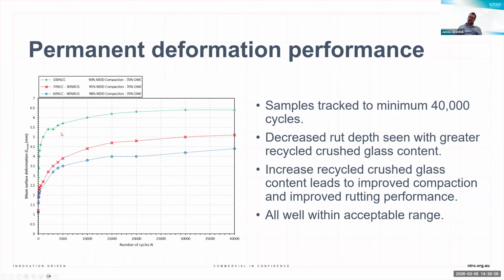Actually, the 100% recycled crushed concrete wasn't that bad in terms of permanent deformation performance under the heavy wheel loading. The test that we undertake, we test under up to 40,000 cycles. Typically, the correlations have shown that if we can get under 14 millimeters of deformation after 40,000 passes, that the material is likely to perform well in the field in a sub-base application. So actually, although the recycled concrete didn't look that great, it probably would have performed okay in the field. But now we can see that we've blended it with recycled crushed glass and we get improved performance.